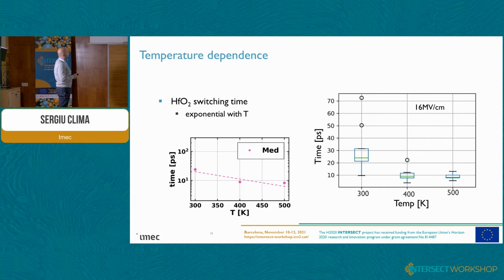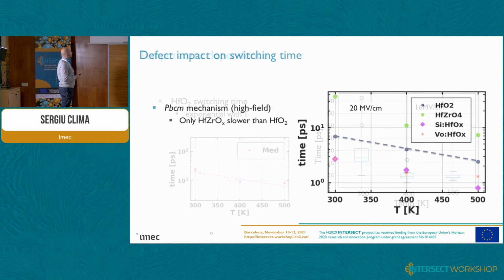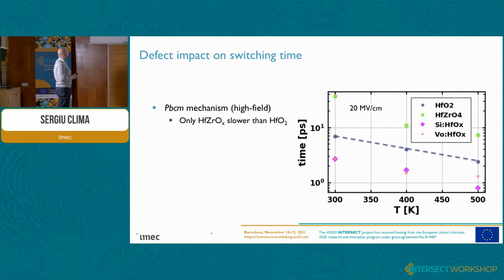We do the same for different temperatures of the material, and we see the same exponential behavior. Whereas for different materials, in this case, I should say that we did not relax the strain, because, for example, if we substitute the zirconium for hafnium to have the hafnium zirconate, or if you put doping of silicon or oxygen vacancies, the strain in these systems will be different. So there will be a large difference compared to what I have here.